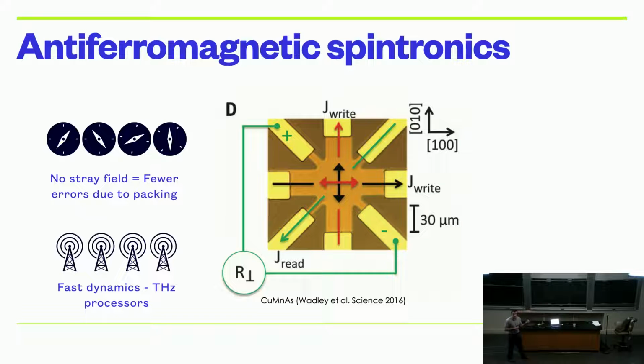And what a series of papers about 10 years ago demonstrated was that you can make a piece of magnetic memory from an antiferromagnet, in a device that looked like this. You could flood current. This is an antiferromagnet known as copper manganese arsenide, and you can make this little 8-prong device. What they do is they flood current east to west, or north to south, and they measure a change in the resistance. And their signal looks a bit like this.